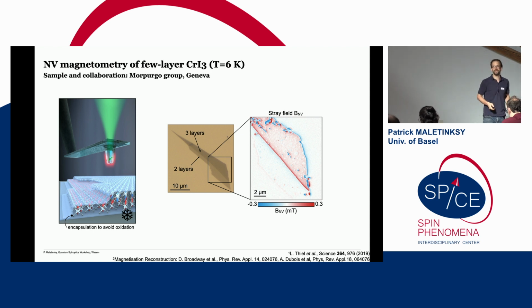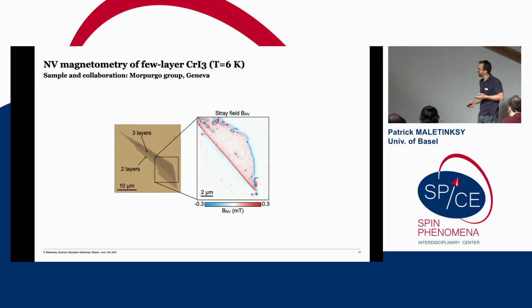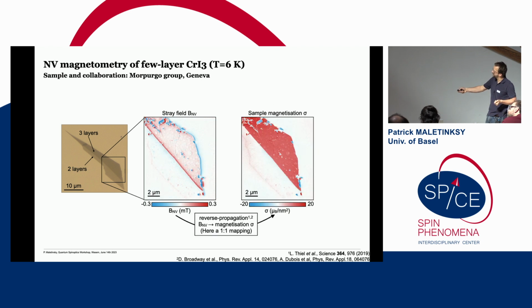Still, we're typically much more interested in the underlying magnetization pattern, but luckily one can actually invert that problem. We can transform this measured stray field map to the underlying magnetization pattern by a technique called reverse propagation. I will not go into the details here. I just want to stress that this is not always an easy task, in part because it is not always a one-to-one mapping, so there's not always a unique solution. But here, in the case of an easy-axis out-of-plane magnet, there is such a solution, and here you see the outcome of it. I also want to highlight that we've been working on this inverse problem for quite some time. Here are some references, and today we're more routinely applying machine learning algorithms to optimize that and also improve the quality of this reconstruction.